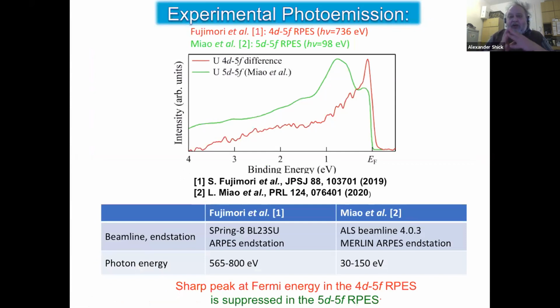So let me go to the experimental results. There is some controversy in experimental data regarding the photoemission. Here is angular integrated photoemission by Fujimori from Japan and by Miao from the United States. One is taken at the 4D5F edge and corresponds to a photon energy of 800 volts. Another is taken at the 5D5F edge and corresponds to 100 volts. And you see the difference is actually huge, in the sense that there is no peak near the Fermi level in the Miao measurements, while there is this peak in the measurements of Fujimori.